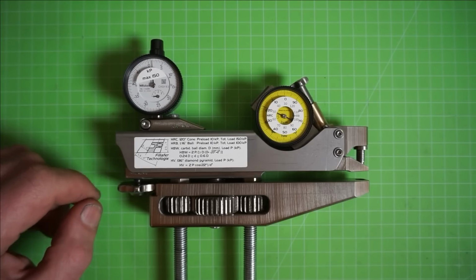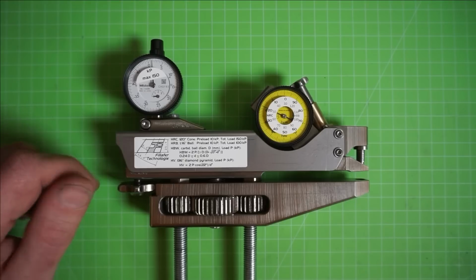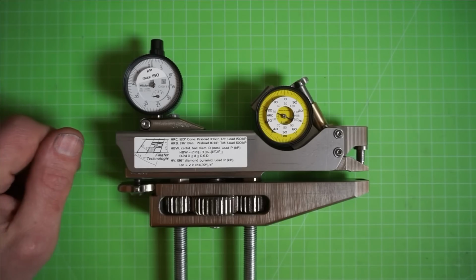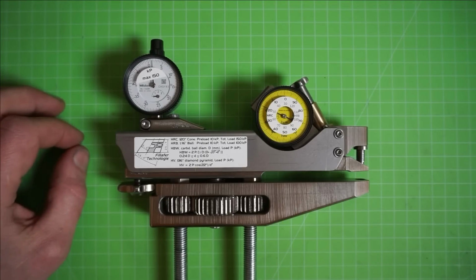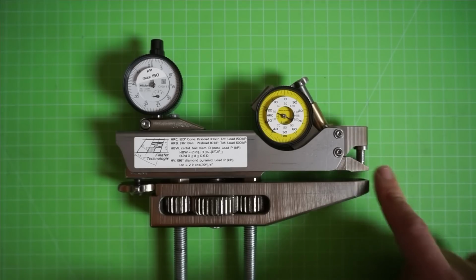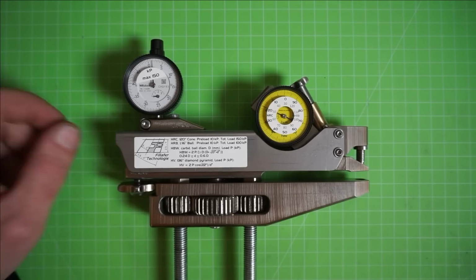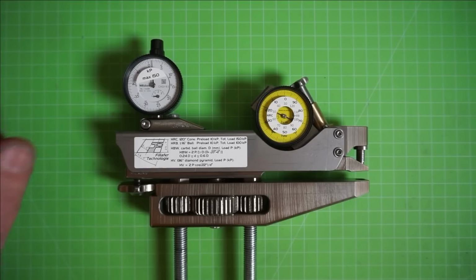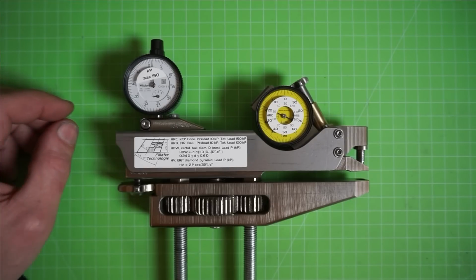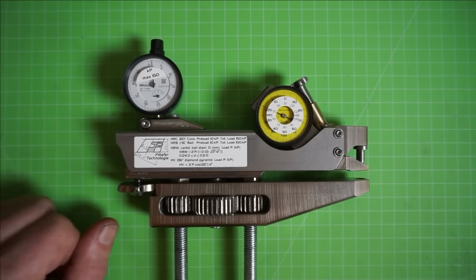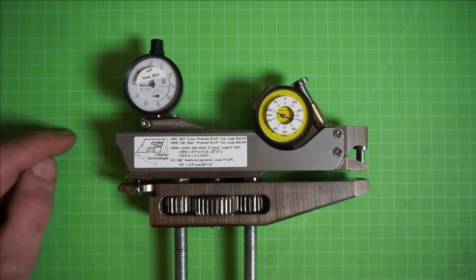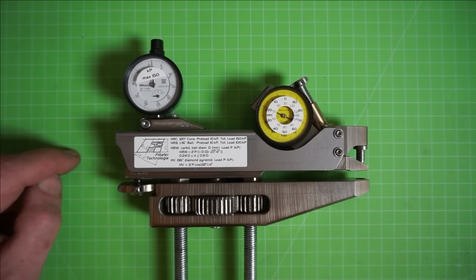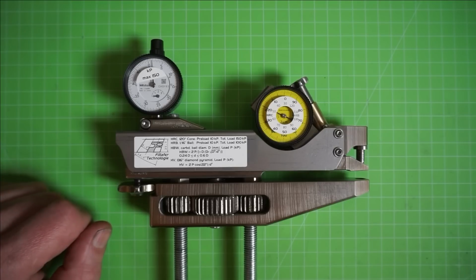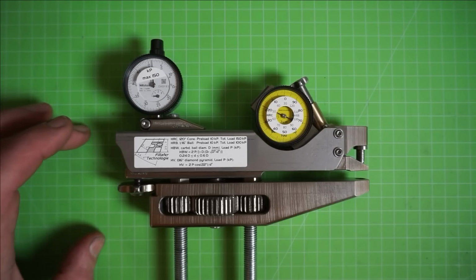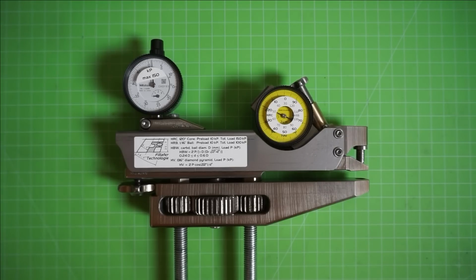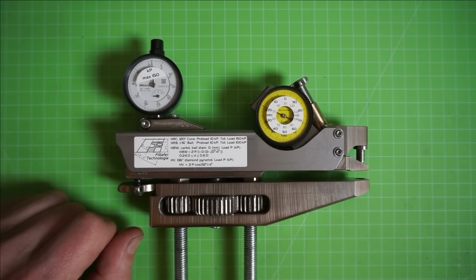So the other most common hardness testing methods, which are the Brinell and the Vickers hardness tests, get rid of this problem by not measuring the depth with which the indenter sinks into the material, but rather we measure the size of the indent, then compute the surface area of the indent, and compute the ratio between indentation force and surface area of the indent. And this is more related to material strength than what we do with the Rockwell tests.